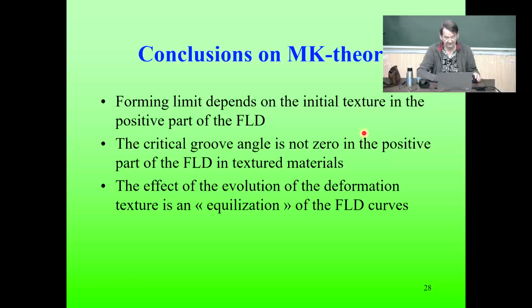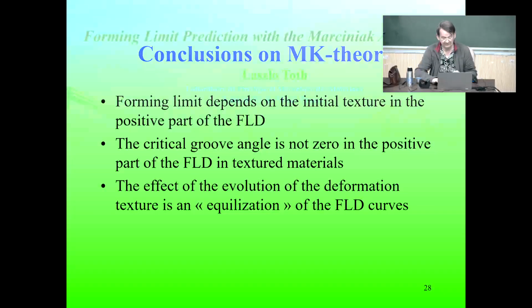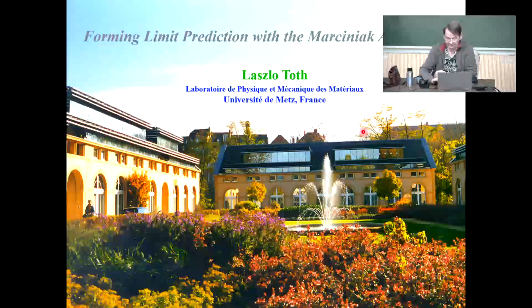So these are the conclusions on the Marciniak-Kuczynski theory, that forming limit depends on the initial texture. In the positive part of the FLD, the negative is basically independent. The critical groove angle is not 0 in the positive part, opposing Hill's theory. And the effect of the evolution of the deformation texture is kind of an equalization of the FLD curves. So this was an old work, it was a long time ago.